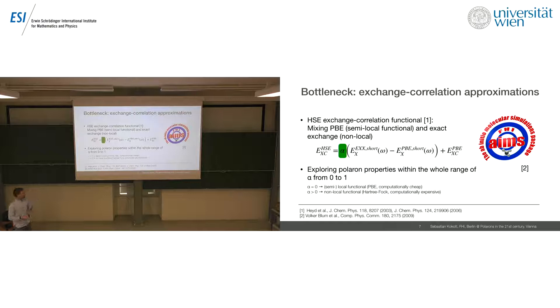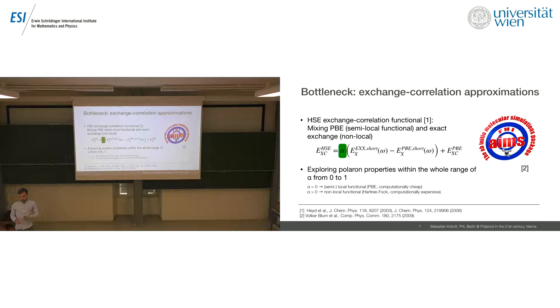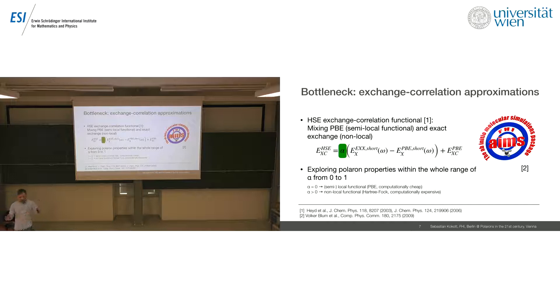To study the dependence on the exchange correlation functional, we use the so-called HSE functional, which mixes a fraction of exact exchange with the PBE functional. One important thing to know is that the PBE functional is quite cheap - you can simulate systems up to 10,000 atoms nowadays - but if you turn to HSE, this is really very costly and you need a lot of computational power. We change this mixing parameter alpha, and for alpha equals zero you basically get the PBE functional, which is cheap. Whenever you have any fraction larger than zero, you have this expensive calculation.